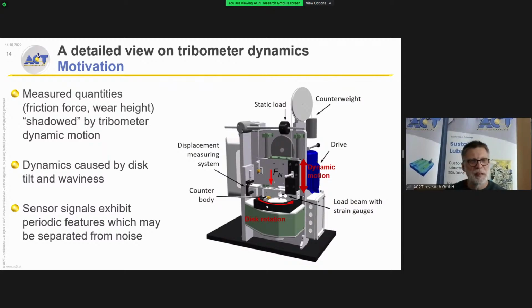So it means that the friction force and the normal force, for example, is actually what you measure is a contribution of the actual contact forces you have, but then to some extent also the dynamic forces in the system. And if you analyze these kind of signals carefully, you can actually separate some periodic features from the actual, let's say, signal which you want to detect. And if you do that, you can actually reduce what is an apparent noise in the signal.